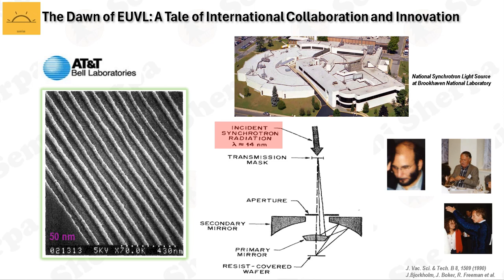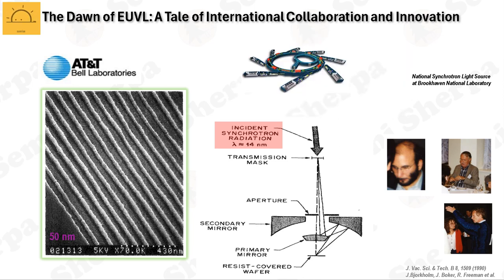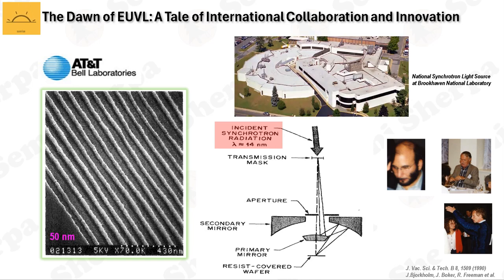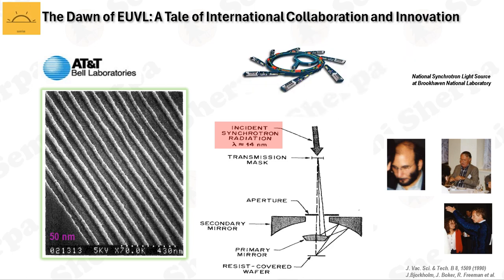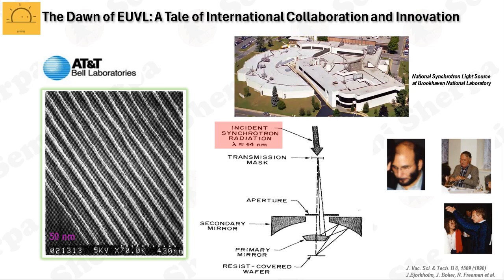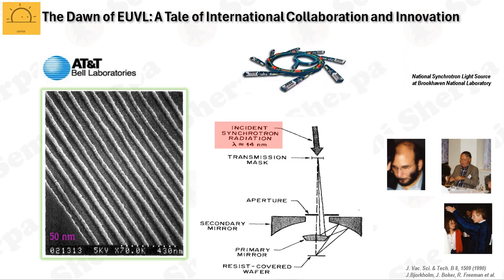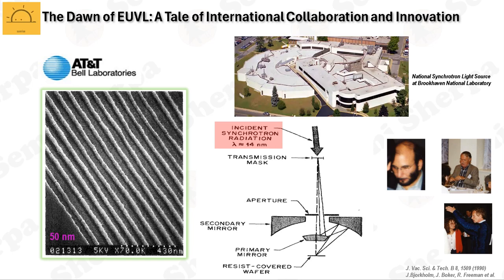By the next year, AT&T reported achieving a nearly diffraction-limited 50 nanometers pattern with soft X-ray projection lithography, SXPL. Undulator radiation at 14 nanometers from a synchrotron storage ring and a two-mirror Schwarzschild objective were used to print features as small as 50 nanometers lines and spaces in photoresist at a reduction of 20:1 from a transmission mask. Both Kinoshita and Wood later referred to that evening in Monterey as the dawn of EUVL.